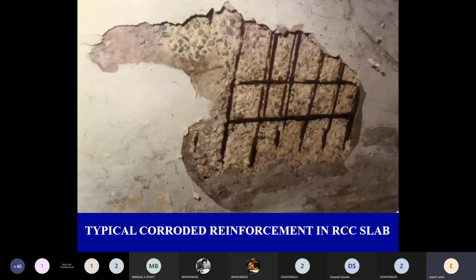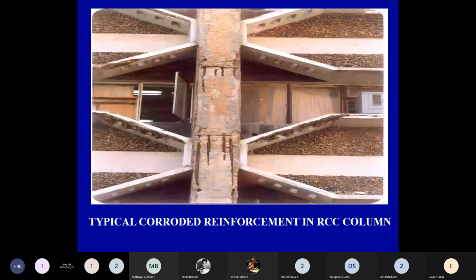So here this slab was treated as plain concrete. Since the reinforcement has completely gone, ISMB sections in both the directions were kept to just hold this slab and make sure that it at least sustains for 15 to 20 years. You must be hearing in the news that the new parliament building construction is underway. So that was the reason that the government decided to construct a new parliament building, because this has almost completed its service life.